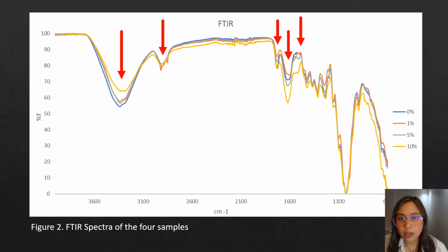Due to the treatment, there is a reduction in the hemicellulose and lignin found in the Salago fiber. There was a partial removal of the amorphous region in the structure of the fiber due to the shifting of the peak to a higher wavenumber.